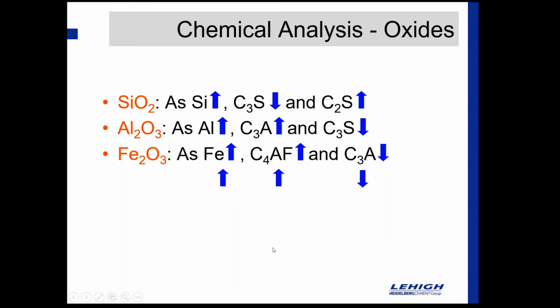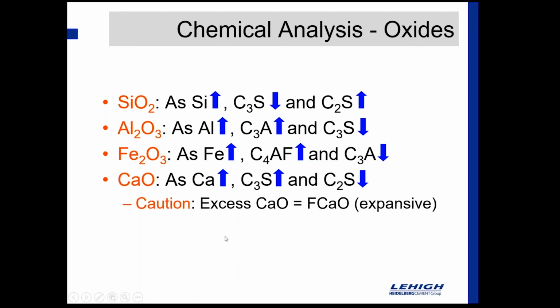In terms of the iron content, I can raise the iron. When I do that, I raise the C4AF, so I'm going to make a little blacker cement, but at the same time, I'm losing C3A content, and now I've lost some of my early strength gain or the potential to generate heat. Lime is the big one. As I raise my lime, the C3S goes up and C2S goes down. And again, that means I've got an increase in early age strength, but potentially a drop in my later age strength.